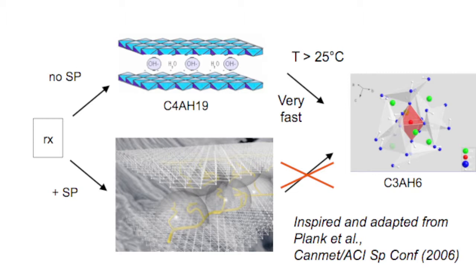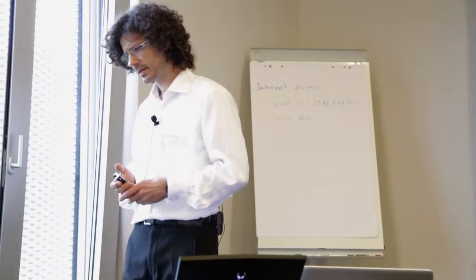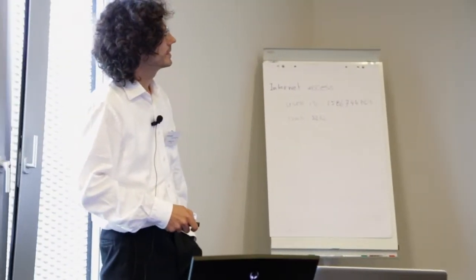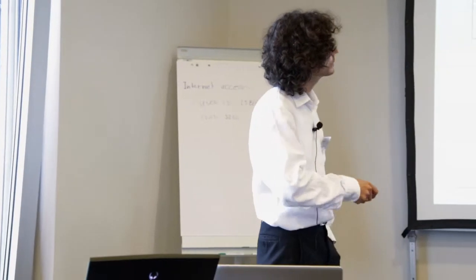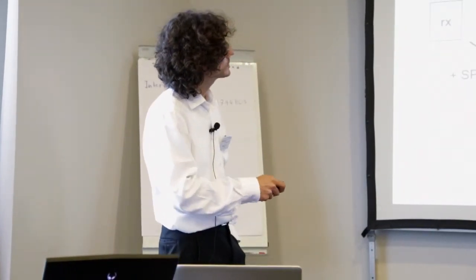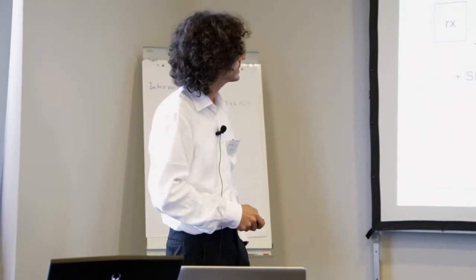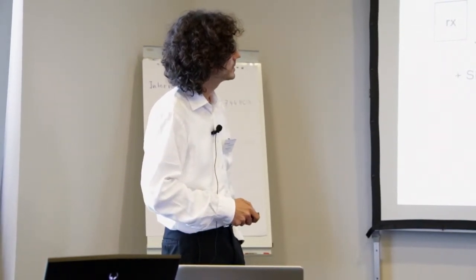Now what I would like to move to is the work that came out in this publication and was really coming out of this core project from Nanocem. And I try to emphasize the specific contributions of this project. And here I wanted to put that other slide before. That was just summarizing what Professor Flatt reported, and we also found that under normal conditions, the laminar phase will convert to a cubic phase, but in presence of the polymer it is stabilized, and this conversion does not take place.